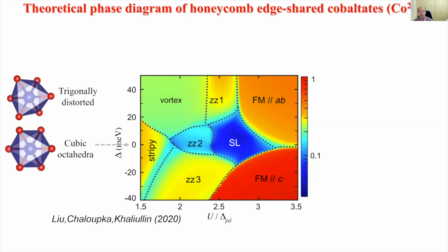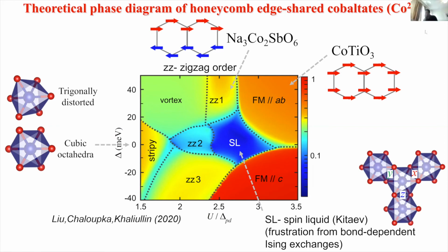So the trigonal distortion is not introducing competition between the Ising bond along this direction and the Ising bond along that and the Ising bond along this. But it's actually introducing Heisenberg terms and gamma terms and so on that are competing with the Kitaev terms. But all this trigonal distortion actually maintains the symmetry between these three bonds. But the interaction is no longer Ising-like, but mixed in. So in this case up here is strongly in the plane, and in this red region here is strongly along a common c-axis.